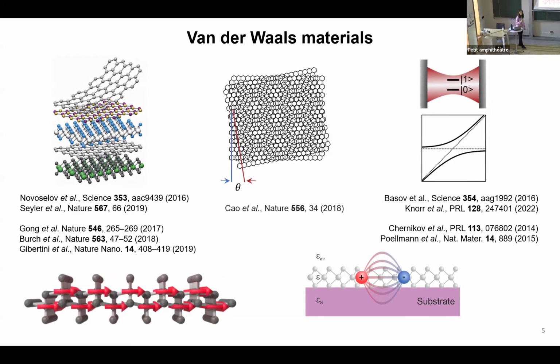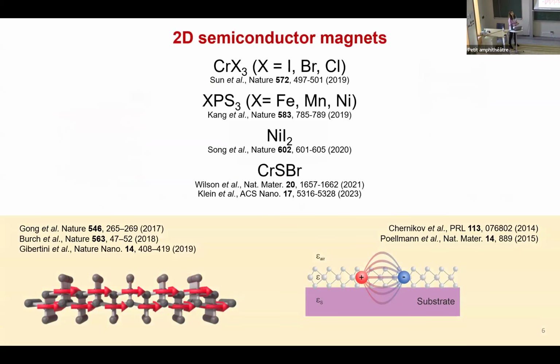Here, the vast catalog of van der Waals materials has been completed by the discovery of magnetism in two dimensions, which for a long time was thought not to be possible due to the Mermin-Wagner theorem that forbids the formation of long-range spin correlation in the low-dimension limit. However, due to anisotropic exchange interaction and single-ion anisotropy, we can stabilize magnetism even down to the monolayer of some materials. And what becomes super interesting is when we combine two-dimensional magnetism with semiconducting van der Waals materials. In these semiconductor van der Waals magnets, of which I put some examples here, there are interesting properties of both magnetism together with the optoelectronic properties of a semiconductor.